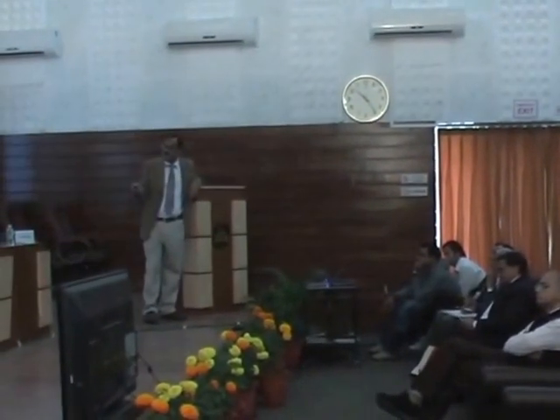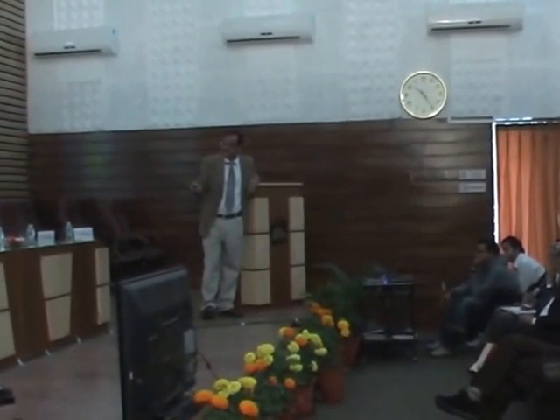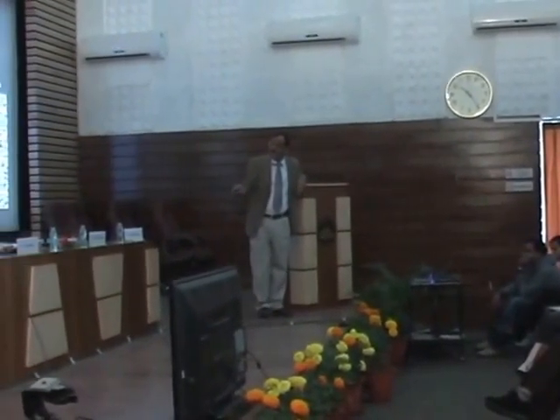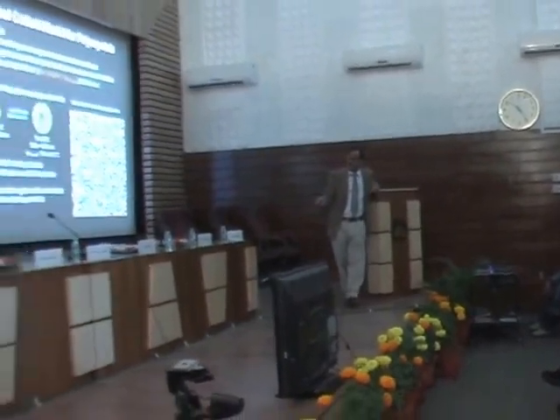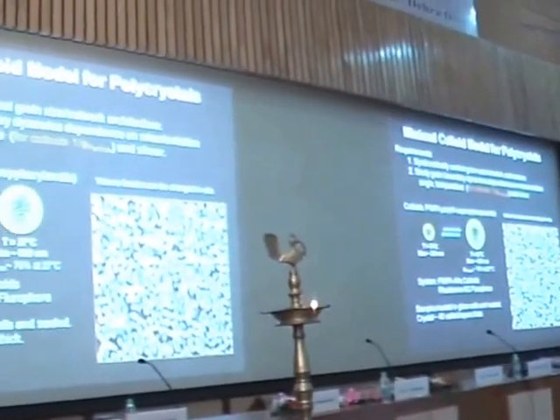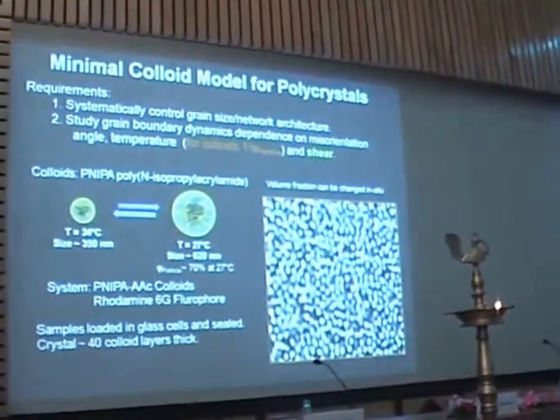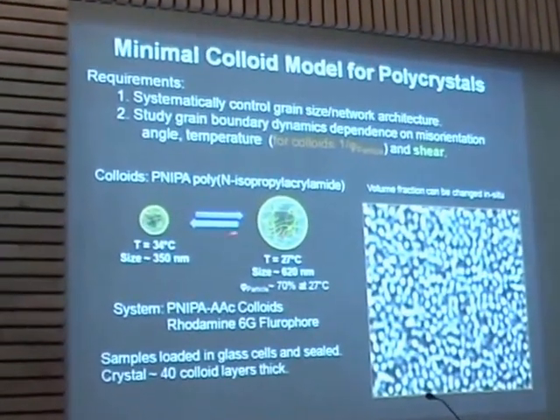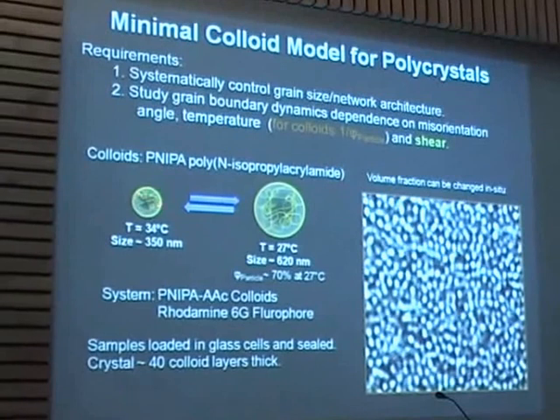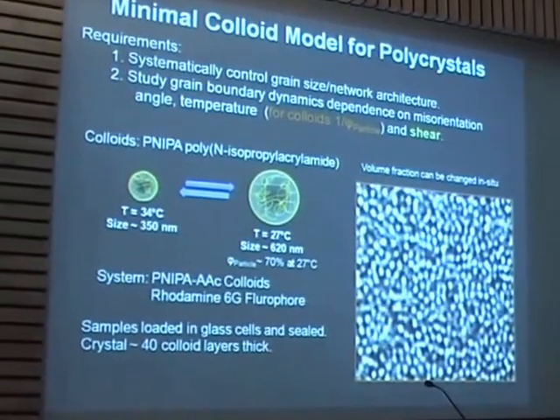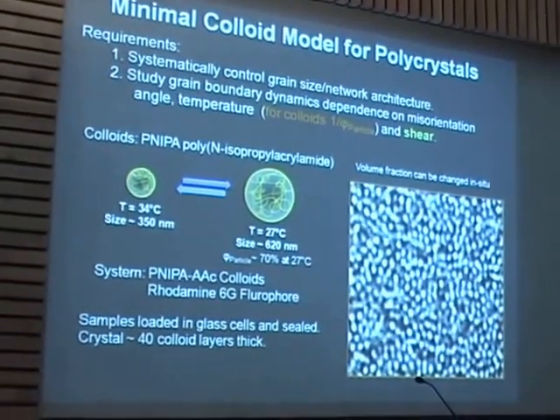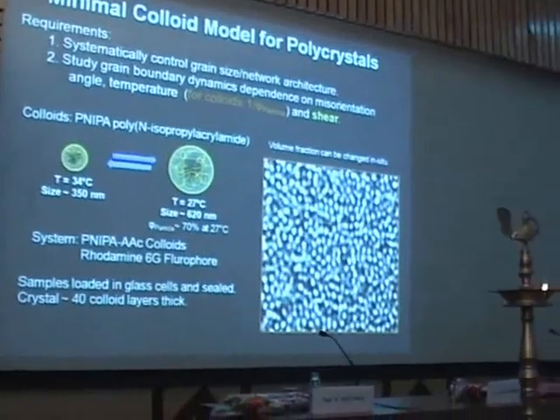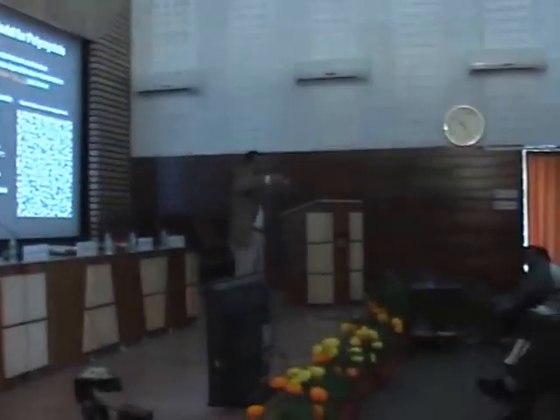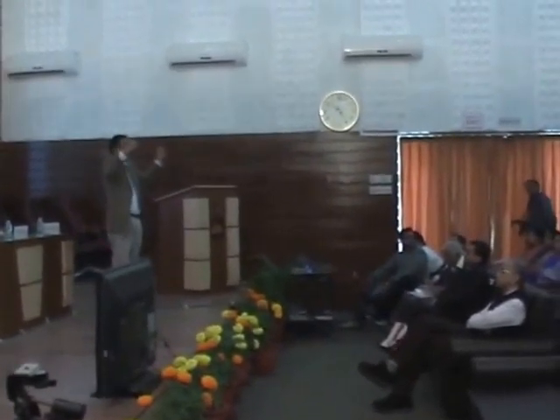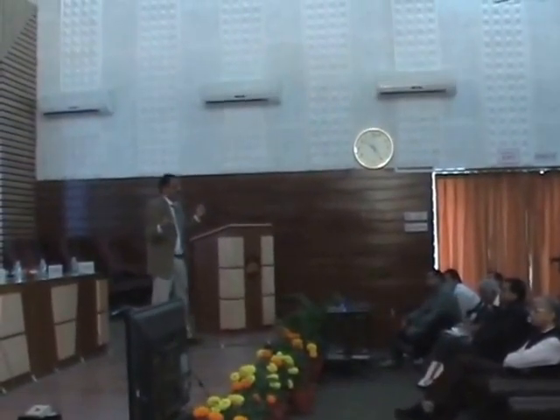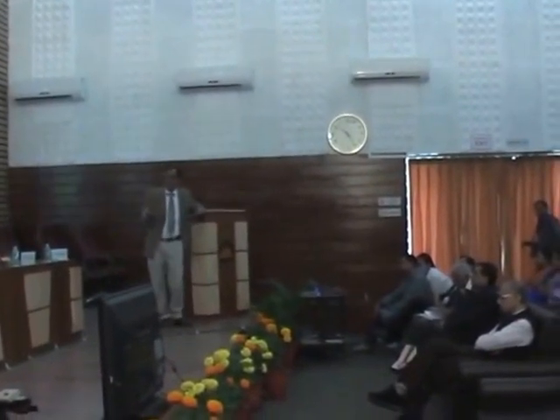So now here in these systems, these particles are made of a polymer whose volume changes with temperature. So when you cool them, it is a much bigger particle. When you heat it, it shrinks. And this allows you to go from a fluid-like phase to a crystalline-like phase. Same system. So you can go through this transition where the particles are free to move, and then they suddenly become a beautiful face-centered cubic lattice. So they form a colloidal crystalline lattice.